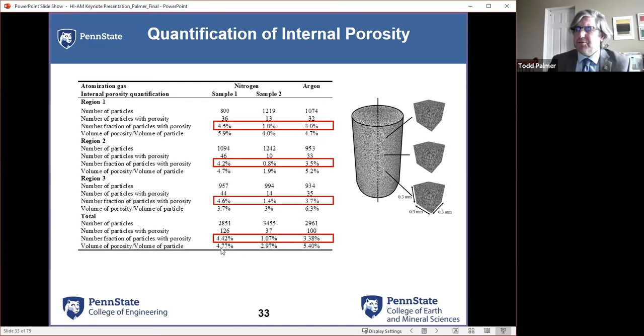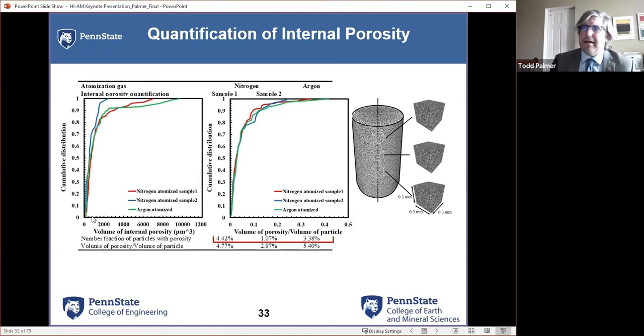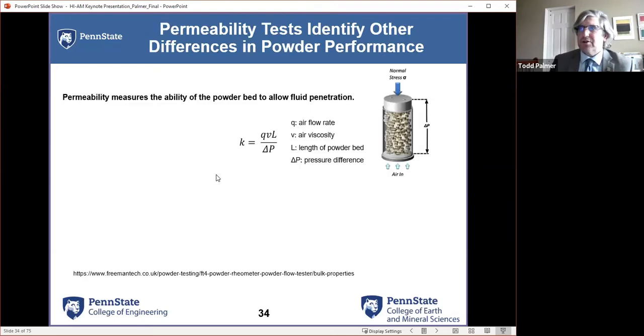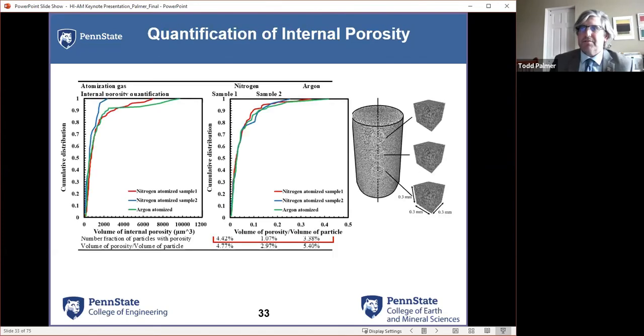but what we tend to see here is that, you know, between about 3 and 5% of the particles by volume have porosity in them. That's 3 to 5% error in mass. You start thinking about that, that can be driving some of these differences that we had. And so we start looking at some of the different number fractions and how they come with a cumulative distribution. We can start quantifying it. And so we can then start thinking in terms of other ways. So we have some pores, and so our mass isn't what we really thought it was going to be.